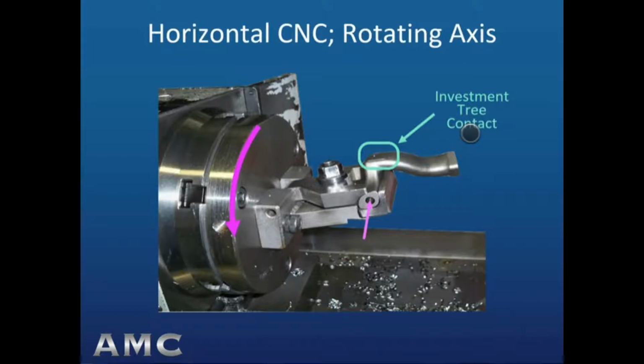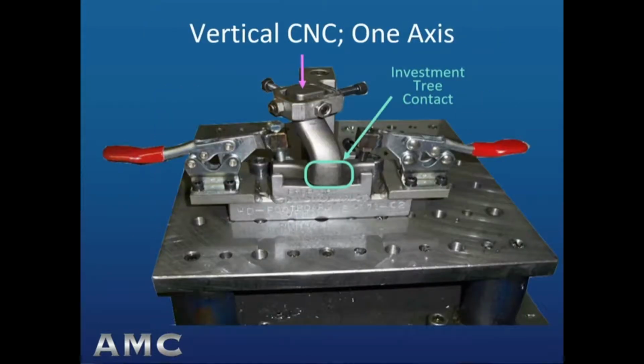The surface is hand cut and hand ground, therefore too wavy and inconsistent in surface profile to be set up against. Here is the remaining setup on a single axis vertical CNC for drilling and tapping of the remaining hole in the vertical leg of the casting's T-bar feature. The hole is located against two adjoining faces at the end of the vertical leg and clamped with screws on the two opposite faces. Self-locking clamps hold the T-fixture in place against the drilling forces.